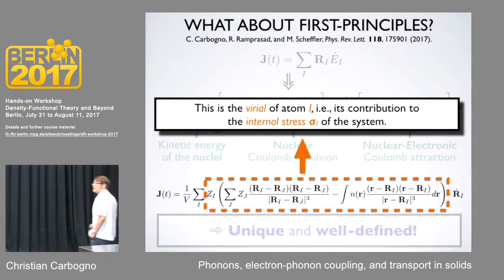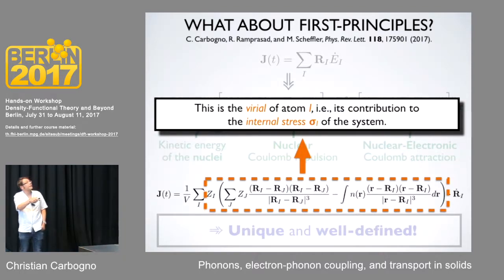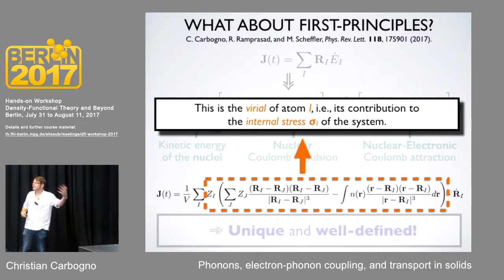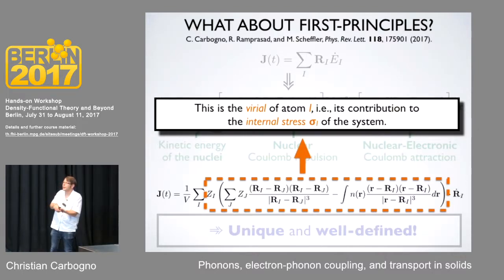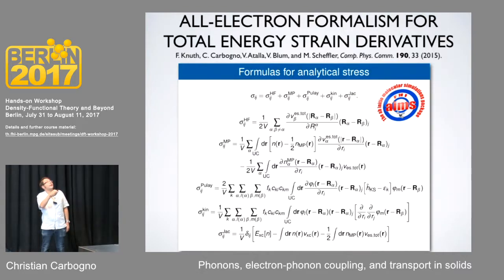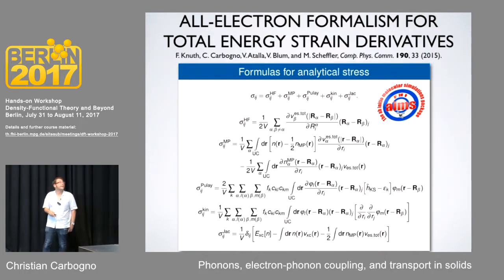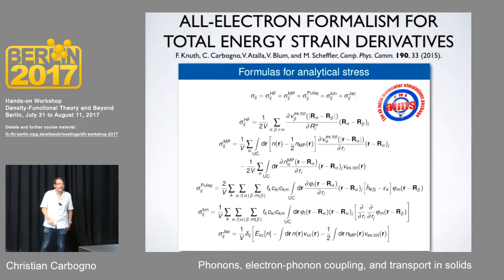In first-principles, you need to define a heat flux. You start from a continuity equation relating local energy to local heat flux, and then decompose your energy — locating each energy contribution at some atom. The problem is that this decomposition is not unique. Going to a first-principles fashion you get an energy density expression, but for the same reason you get gauge-dependent energy densities. One way around this is to go from the simple definition of heat flux to looking at the microscopic details. Taking the time derivative into the sum gives two contributions: one is velocity times energy (convection), but in a bulk solid no atom travels on average, so you can neglect this. What you're left with is essentially the derivative of energy times position, and this derivative is unique.